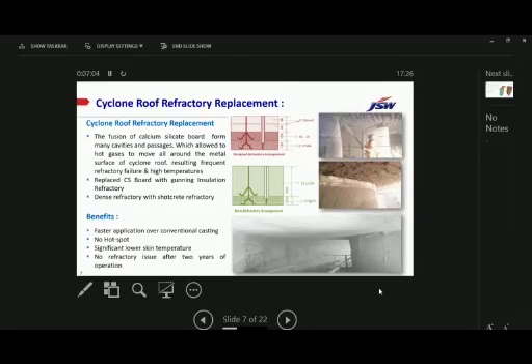That's why it fuses whenever it comes in contact, which leads to the cutting of anchors, and that will lead to refractory failures. So to overcome these problems, a frequent failure of refractory, we adopted the gunning method over the conventional casting method.